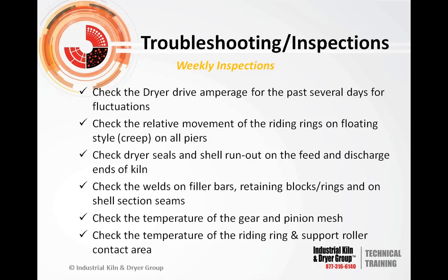It's not a bad idea to check the welds on filler bars or support pads, wedges, whatever you use to mount the tire, and on the retaining blocks, stop blocks, or the rings that hold the tire on the shell. At the same time, it's not a bad idea on a weekly basis to check any welding, like the shell seams, especially on units that have a lot of temperature, because the temperature expansion and retraction can cause weld seams to crack.